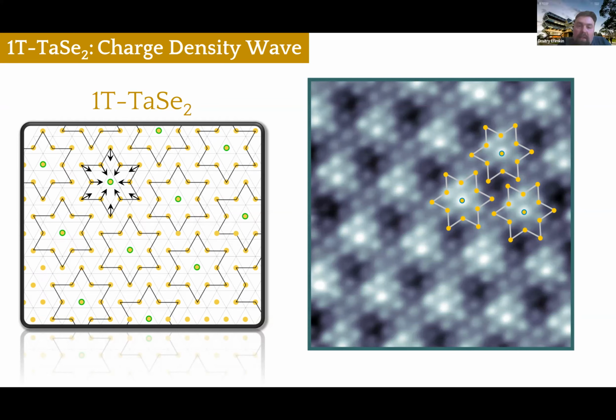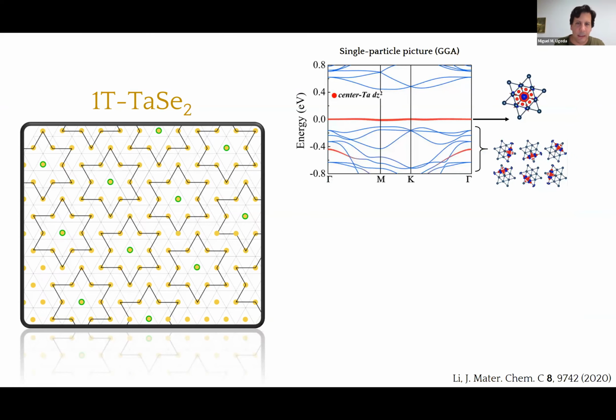So what's so special about the charge density wave? Basically, there are 13 atoms in the new supercell. That means each of the tantalum atoms contributes to this supercell with one electron. And therefore, if you carry out the band structure of this material, there is the formation of 13 new bands.